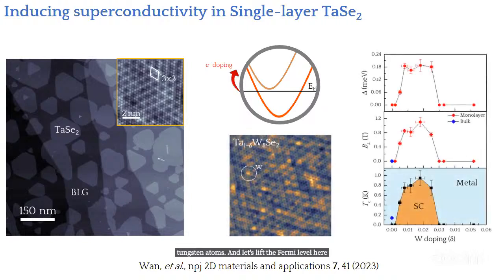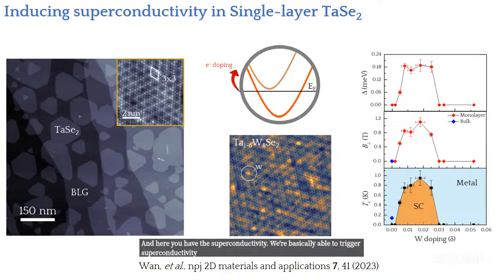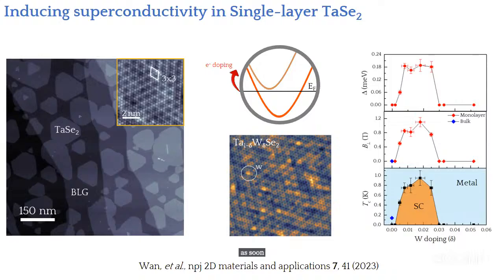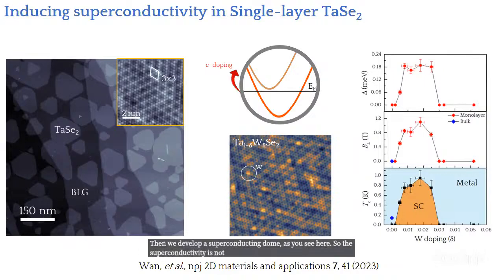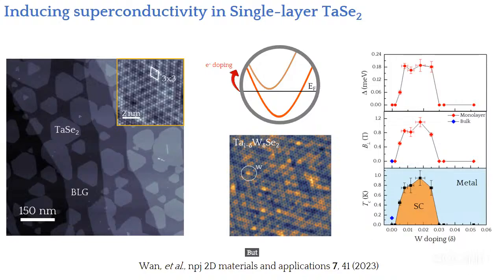Okay, so here you have an STM image of tantalum diselenide, and again, these triangular features correspond to tungsten atoms. And here you have the superconductivity. We're basically able to trigger superconductivity as soon as we put a little bit, 1% or 2% or 3%, of tungsten atoms in the lattice, and then we develop a superconducting dome, as you see here. So the superconductivity is not very strong. The optimized critical temperature is around 1 Kelvin, but yet here it is.